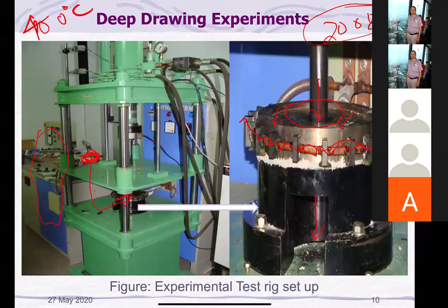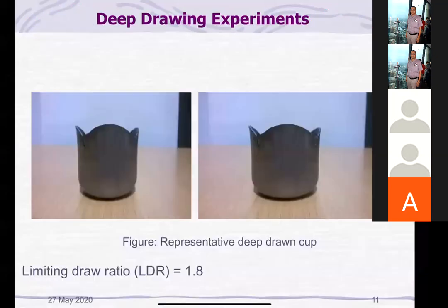The dies are already hot, and the way we are measuring the temperature is by using a pyrometer. Nowadays, pyrometers are quite popular to check the temperature. And during this coronavirus time, everywhere they are using thermal scanning. Thermal scanning means they are measuring the temperature. We have so many such temperature measuring systems to measure the temperature of these workpieces in the die. So this is the setup that we are using.